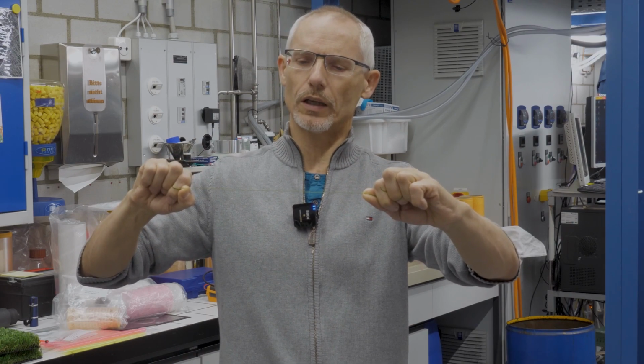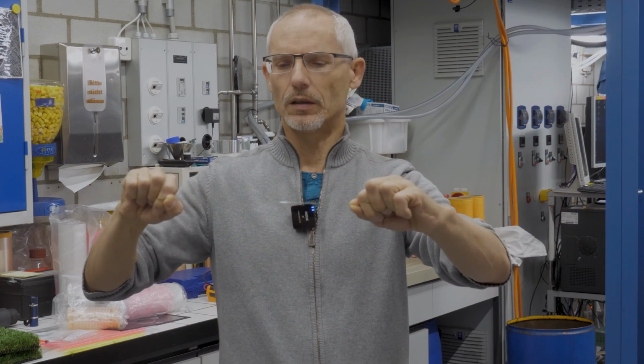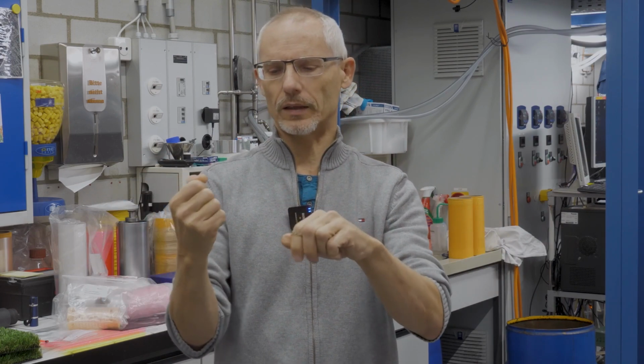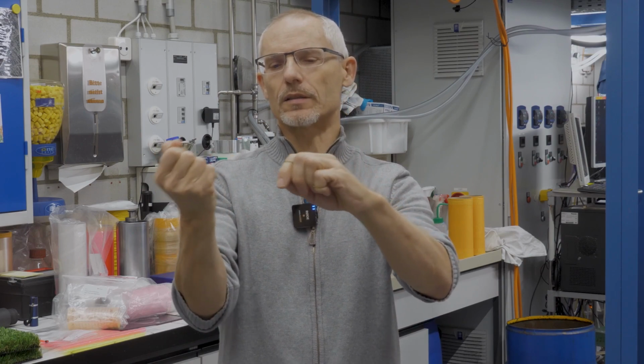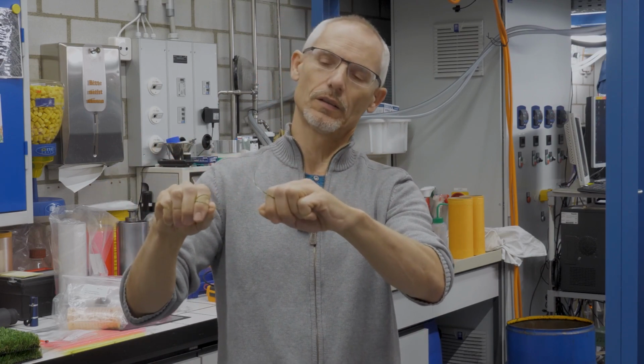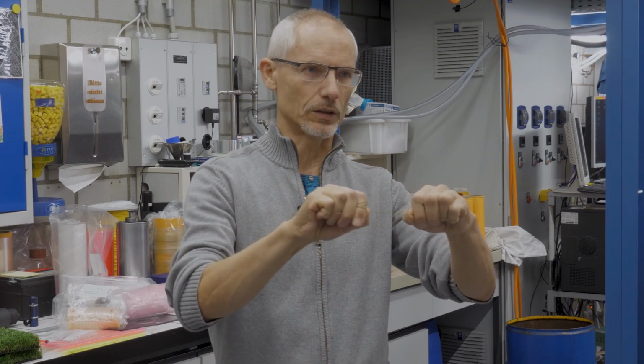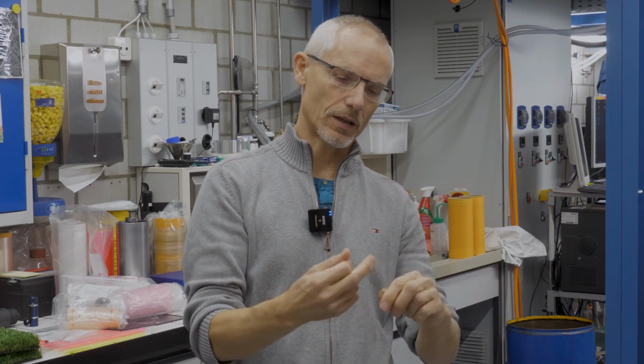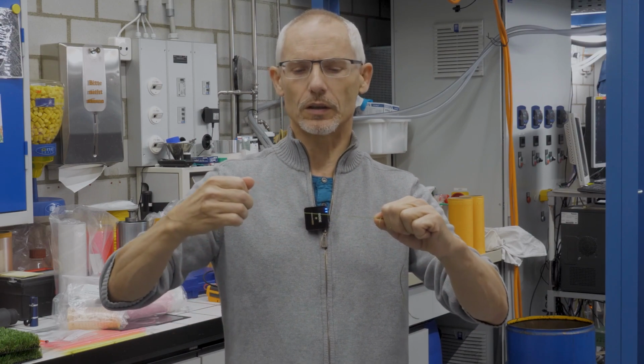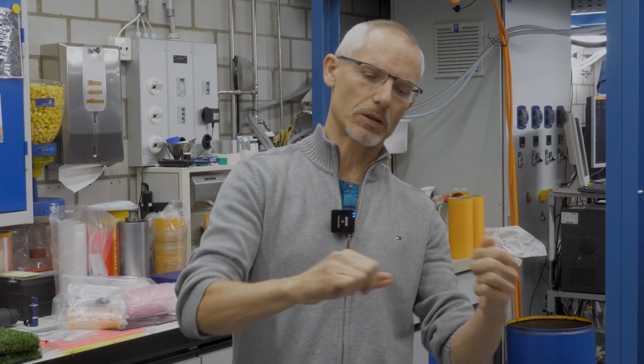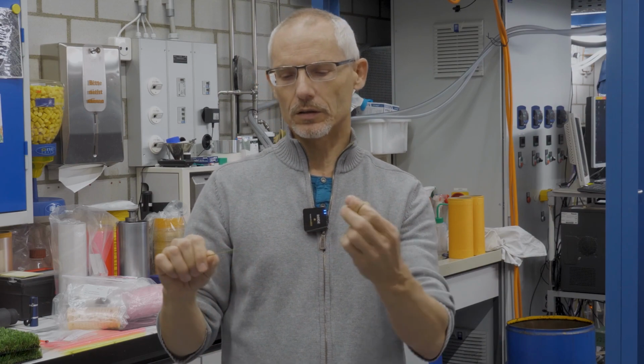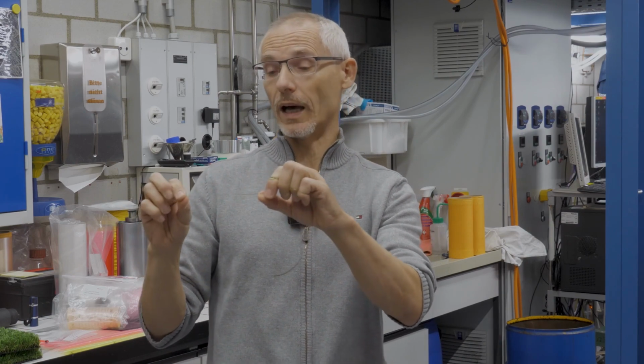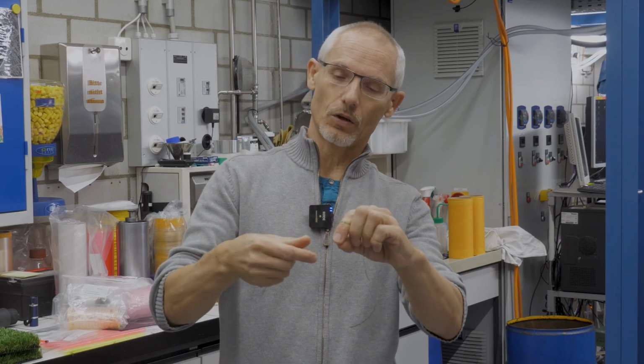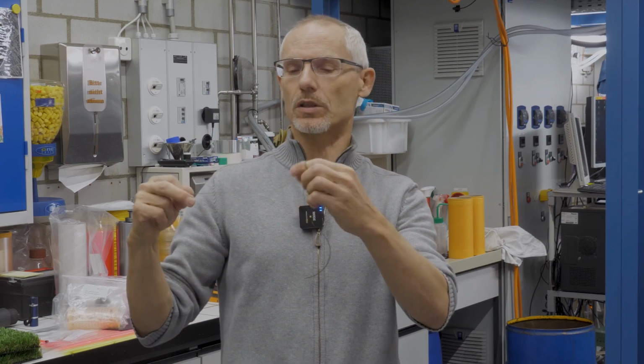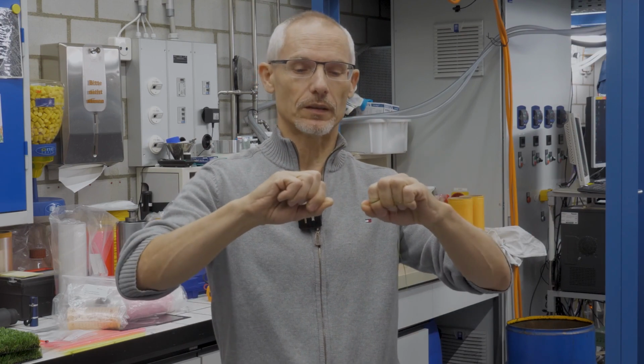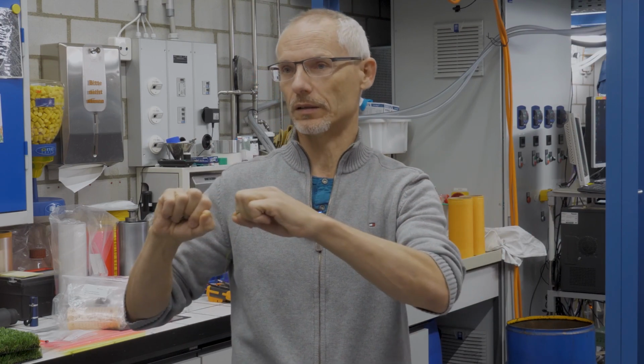But what we actually want to have is a material which is not deformable, but elastic. And as you can see, after having drawn this, we have an elastic and relatively strong material. So after the extrusion, the drawing is also something very important, turning the plastic material into an elastic material. On the molecular level, that means we align the very long polymer chains all in the direction of the filament. And this gives us the elasticity and the high tensile strength.